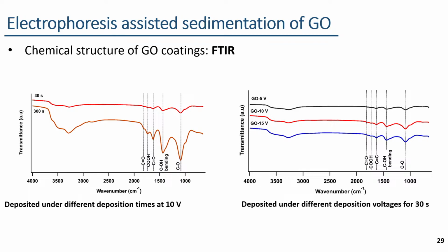When it comes to the chemical structure of these GO coatings, here I have shown the FTIR spectra of these GO coatings deposited under different deposition times and different deposition voltages. In these FTIR spectra, we can observe the IR peaks corresponding to the oxygen functionalities of graphene oxide. That confirms the presence of graphene oxide in these GO coatings. However, we can see that the intensity of these IR peaks increases with the increase of deposition time and deposition voltage. This is due to the increase in the amount of graphene oxide deposited on the anode with the increase of deposition time and deposition voltage.